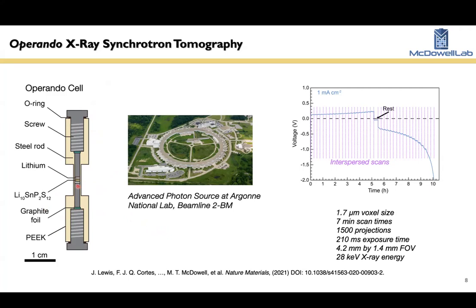They're very small. The diameter of the cell is about 2 millimeters. And it allows us to apply a stack pressure to the cell and seal the cell so that it can be operated in air. And the size is specified so that X-rays can penetrate it and be used for imaging. So these particular experiments we do at Argonne National Lab at the Advanced Photon Source Synchrotron. We make these cells there, and then we charge and discharge. This is some electrochemical data shown on the right. And about every 15 minutes or so, we take a 3-dimensional X-ray scan of the cell.